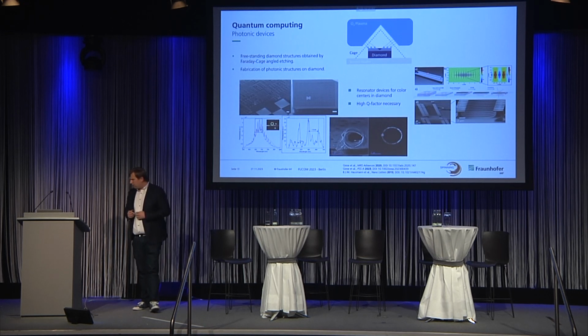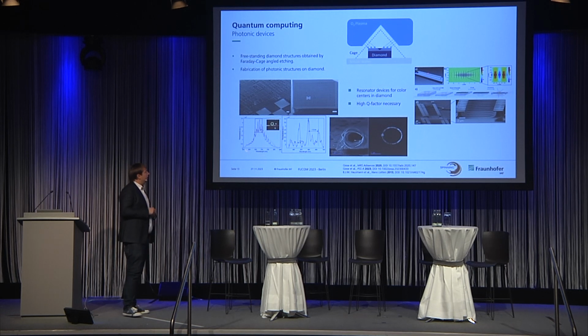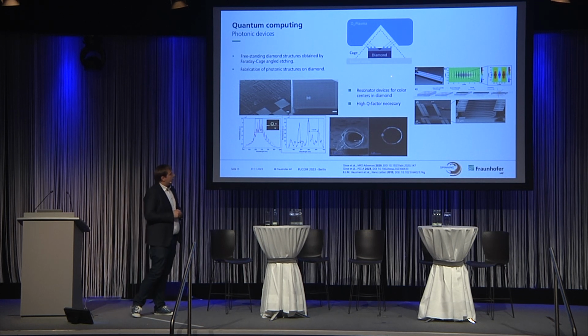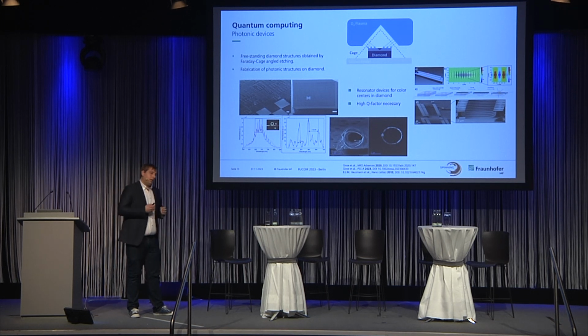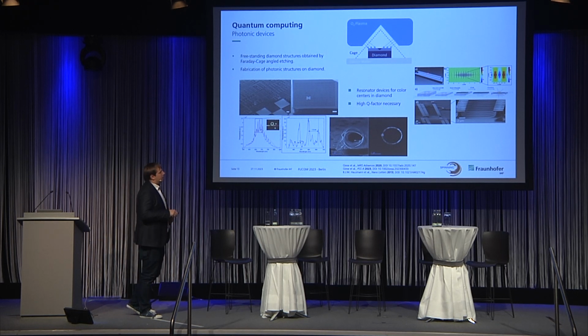How can such photonic devices be fabricated? What you see here are freestanding diamond waveguide systems, like ring resonators with waveguides. You see that even in such simple ring resonators, this is from the NV, you get resonances to the ring. You see over the whole phonon sideband some resonances. So with that, you can fabricate devices that strongly enhance the zero phonon line or the emission of the NV center, and this makes sure that you can entangle these photons in the end. So this is already possible. It has been shown with different resonator devices, and they can be fabricated nowadays with high Q factors. This is not the issue anymore.